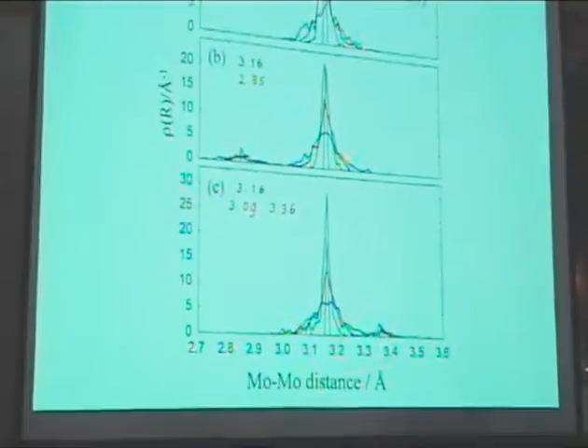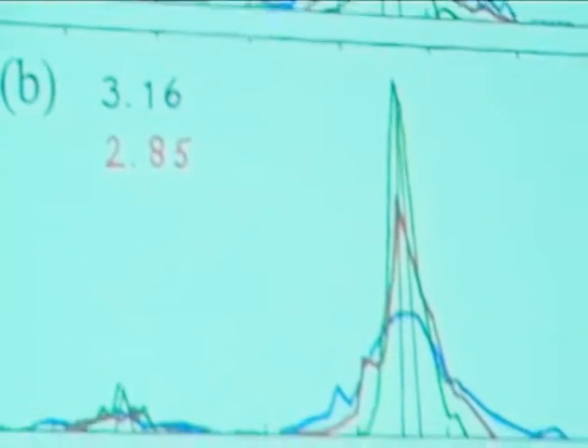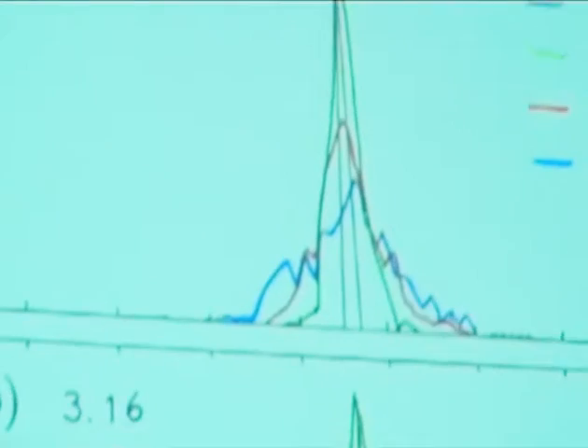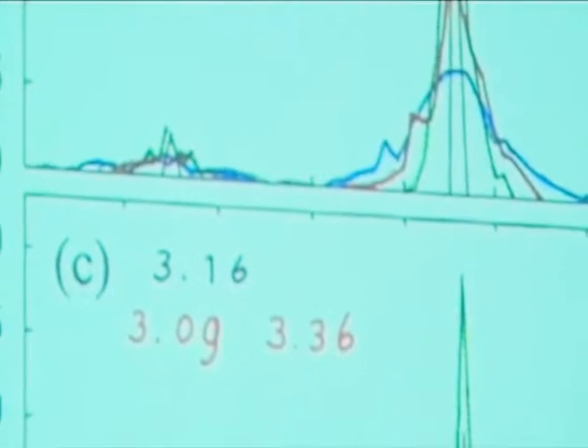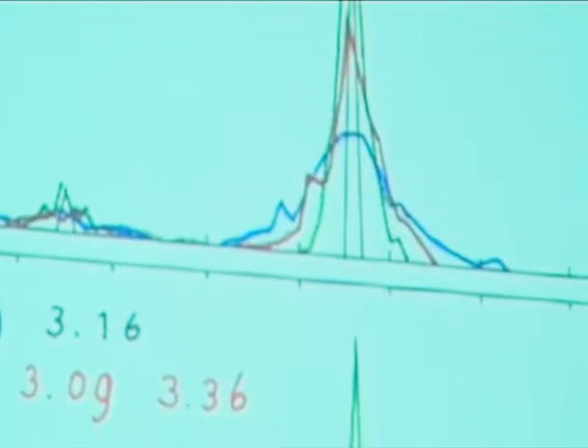This is the model where, in principle, there was no contraction at the edge. So in principle, the average value for the metal-metal distance was 3.16. But we allowed it to randomize by 0.04 angstrom, 0.08 angstrom, or 0.12 angstrom. And since we are counting small particles, you of course do not get a smooth curve. But if we would have done thousands of these particles, then automatically you would get a nice Gaussian curve. But it's on its way to being a Gaussian curve.